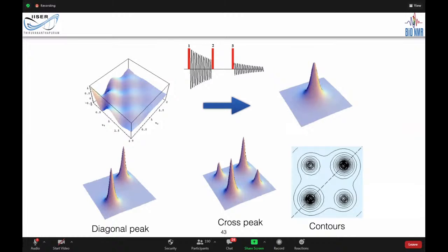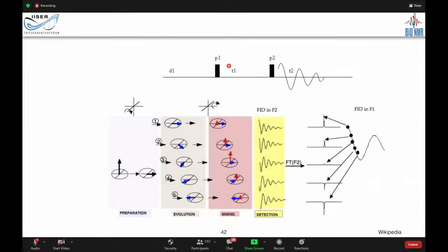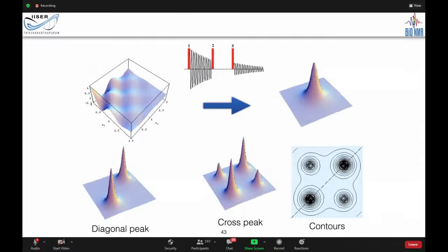What you get in Fourier transform is like this. You get a hill like that. And if you do a COSY, like what we have said, usually there is a diagonal peak that corresponds to the same frequency during what is called the mixing time. Okay. If they have the same frequency during the mixing time, they will come as a diagonal peak. But if they have a different frequency between the mixing time and the direct time, then there will be a cross peak like this. Okay, so a cross peak is these small peaks here. Diagonal peak is like this.